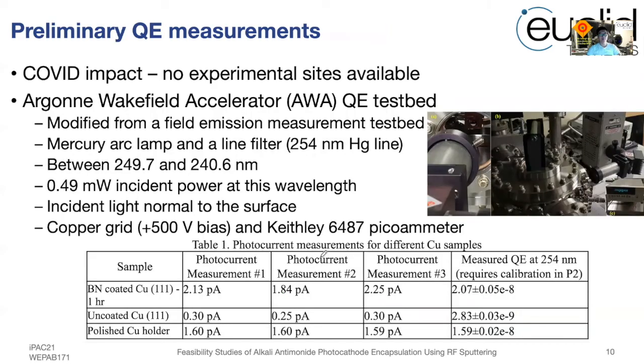After that, we did some QE measurements. Unfortunately, no other experimental sites were available, including the BNL site. So we used our long-term collaborator, the Argonne Wakefield Accelerator, AWA, site for the QE test bed. This test bed was modified from a field emission measurement test bed, and it uses a mercury arc lamp and a line filter, which selects a mercury line at 254 nanometers. The spectrum is between 249.7 and 240.6 nanometers, which is in the UV region, of course. We measured the incident power between these wavelengths to be 0.49, or roughly 0.5 milliwatt.